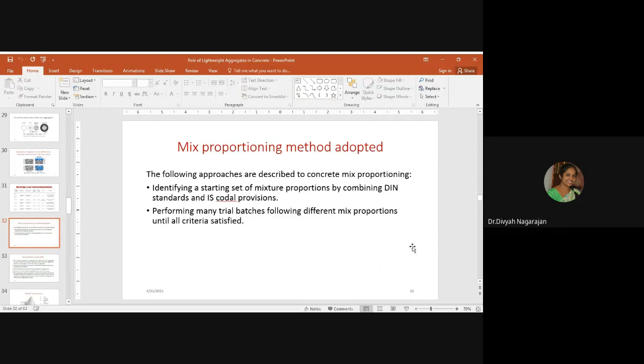So I have done the following approach for concrete mix proportioning. Initially, a starting set of mix proportions were adopted combining the DIN standards and IS codal provisions, and I have performed many trial batches following different mix proportions until all criteria were satisfied. And literature reviews were done extensively, and the values were taken systematically. By following the mix design procedures for lightweight concrete, interaction among the concrete constituents cannot be accounted for. And there is no means to achieve an effectively optimized structure for a given criterion.